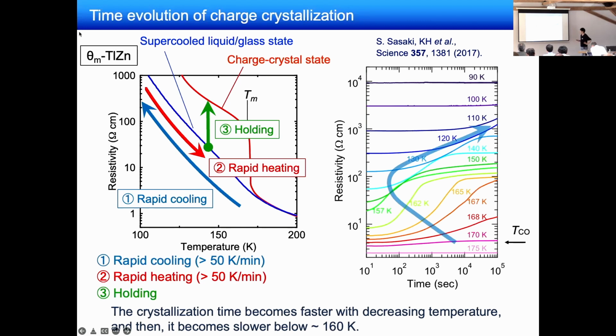We performed this experiment at various temperatures below the charge ordering temperature, and it can be clearly seen that the amplitude of the resistivity, which reflects the degree of charge crystallization, first increases and then saturates at all the temperatures we measured. And this crystallization time becomes slower with decreasing temperature below 150 Kelvin. Then the crystallization time draws this kind of dome shape.